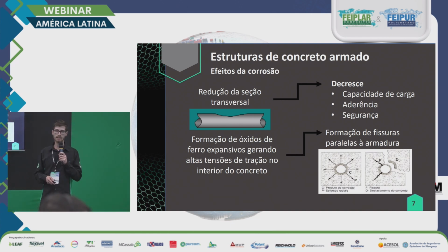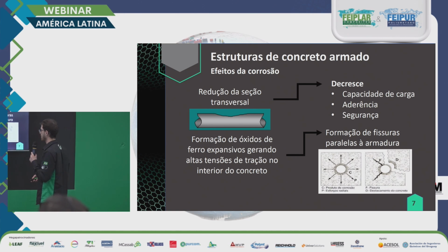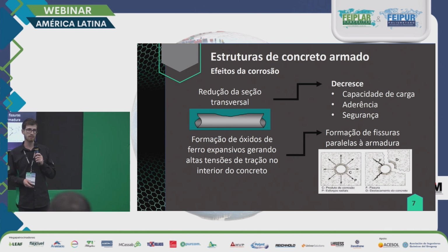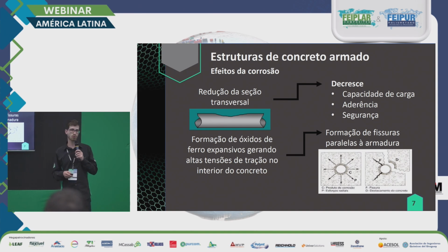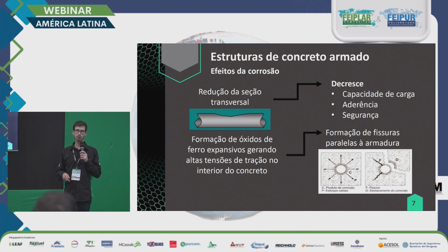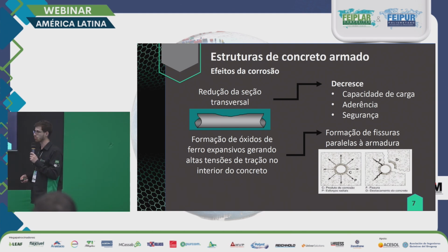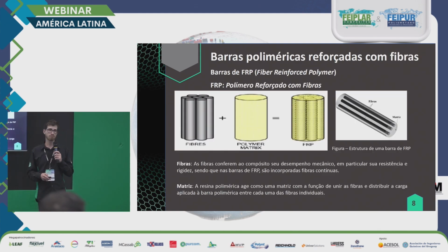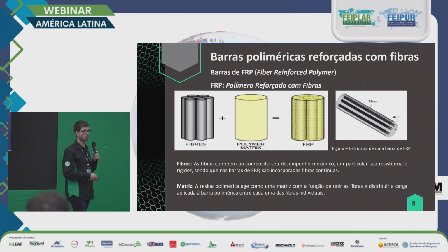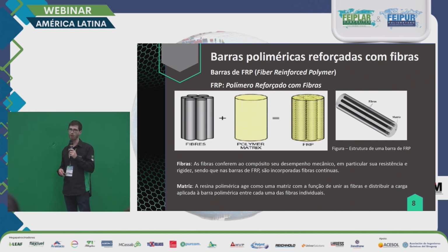The metal meshes, when they suffer corrosion, there is a reduction in adhesion to concrete. And this reduction might compromise safety. There might be fissures in the concrete piece, and these fissures increase if there is no maintenance. This structure will collapse. So that is why composite rebars were developed, fiberglass reinforced.